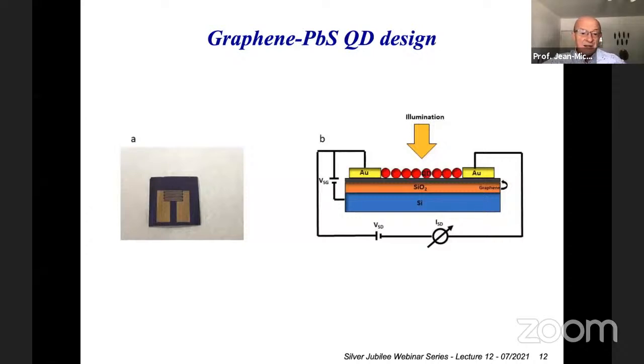And we can design by this way transistors. So you have the two electrodes, the source and the drain, which form actually an interdigitized network to have more conductivity, because the conductivity of a single layer graphene is not so large. It's large per unit surface, but the resistance of a single layer is still kind of large. The resistivity is small. And to have sufficient conduction, so a small resistance, we use a stripe whose total length is a few centimeters. And we can bias the gate and measure the source and drain current.